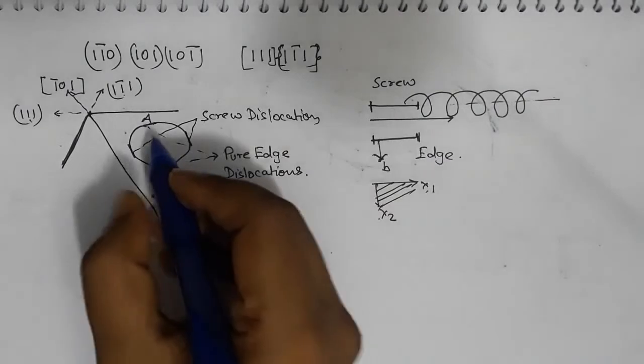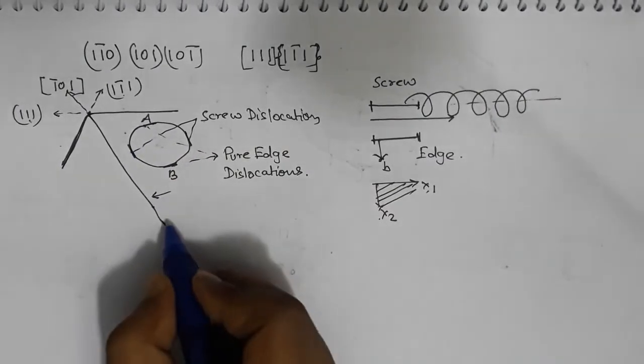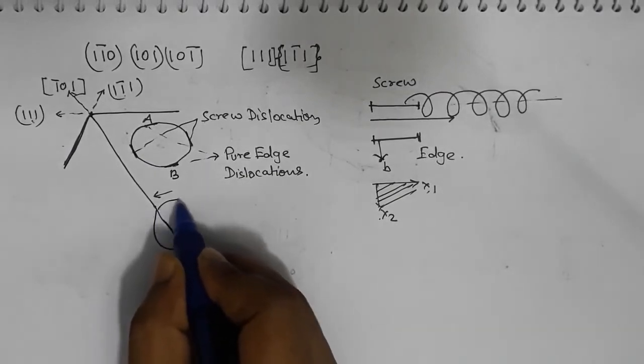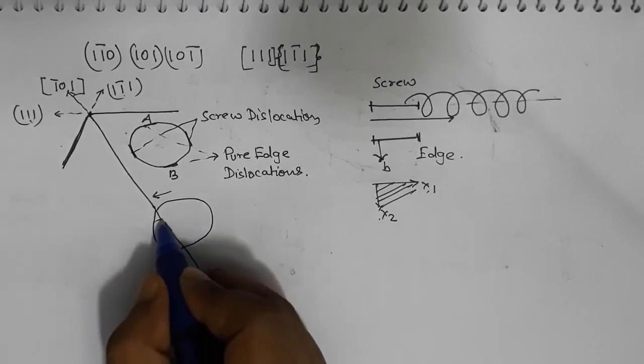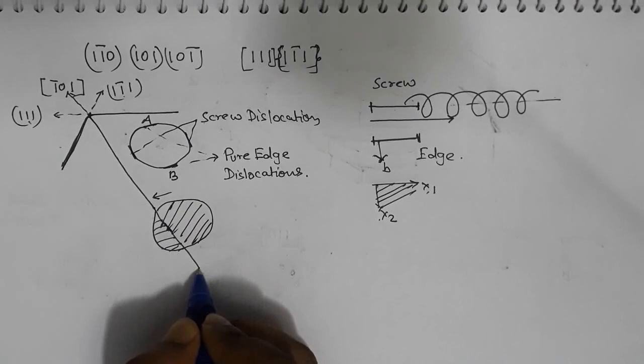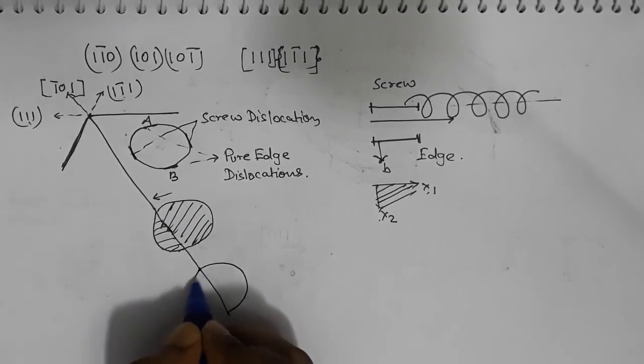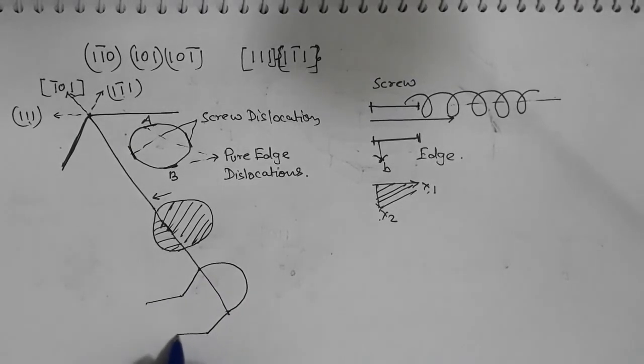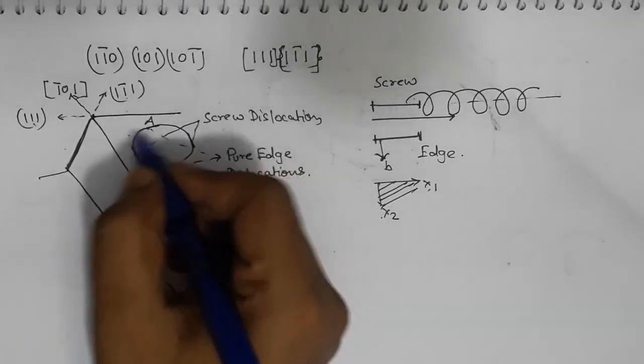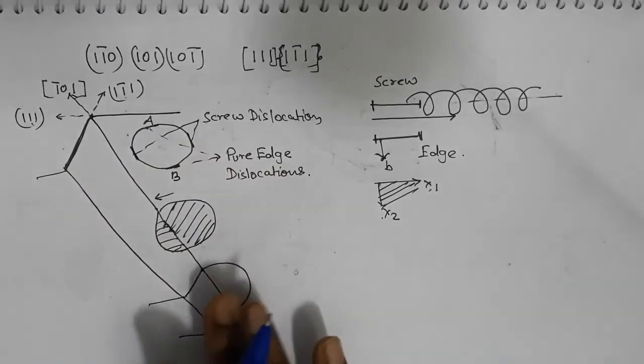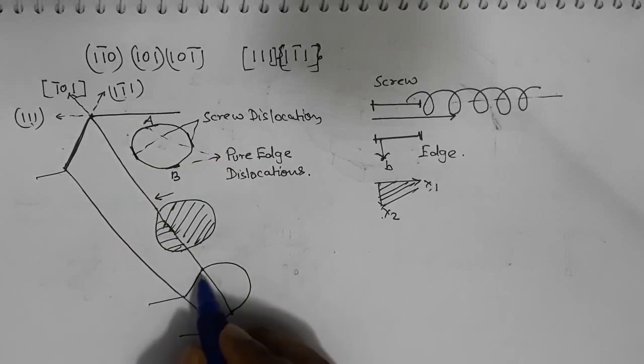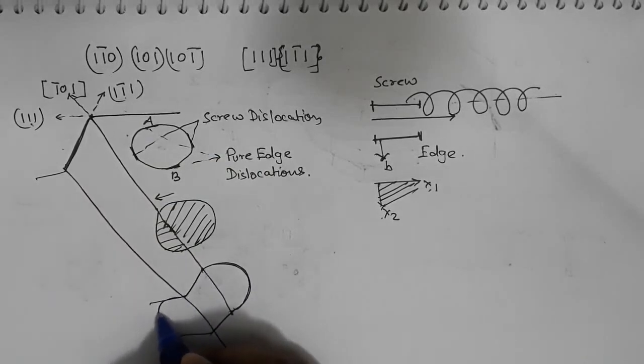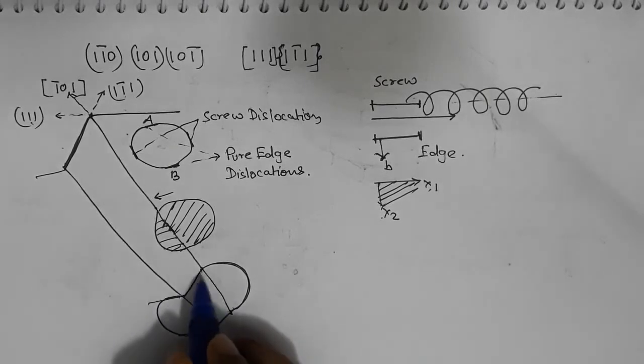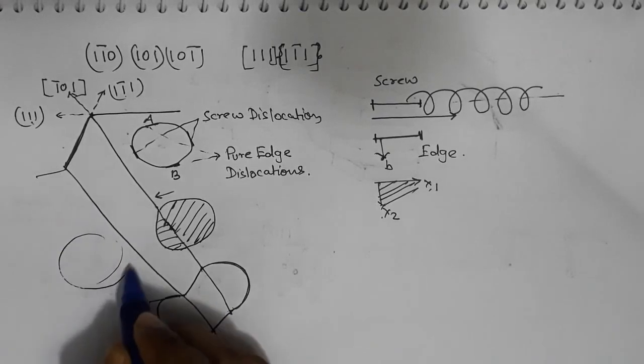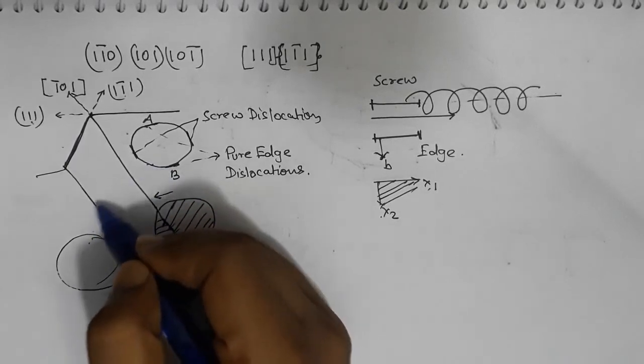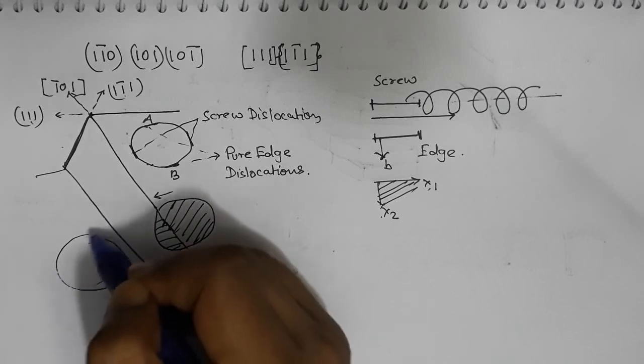So what happens here is that because a screw does not need a plane to move, it will just pass on to another plane, right? And then slowly the whole dislocation may look like this, and then it glides along this plane, and then it comes back to the same plane again. Same plane meaning a parallel plane with the same normal vector, but at a certain distance. So then this dislocation loop has actually moved like this. After some time, the whole dislocation loop will be on this plane, so it would have crossed and come back to another parallel 1 1 1 plane.